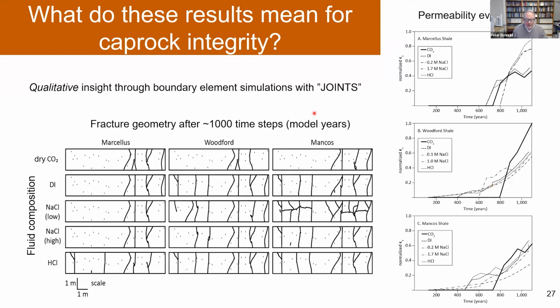One tool that we have is a boundary element code that John Olson wrote many years ago. It's called JOINTS, and it allows us to simulate fracture growth, accounting for the subcritical fracture growth behavior. The code is pseudo 3D. It's accounting for stress in three directions, but the fracture growth is limited to two directions. So in this case, we simulate the fracture growth in a vertical plane, which is what those little diagrams here represent. That would be the bottom of the caprock, that's the top, and the fractures are told to propagate from the bottom up.